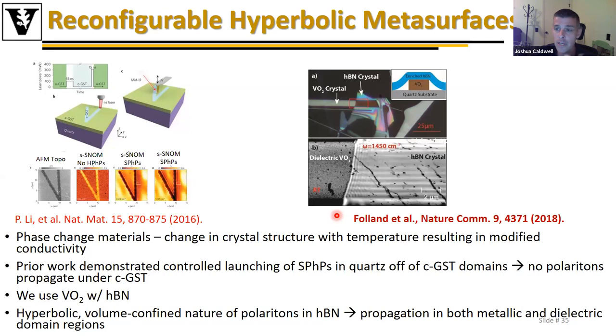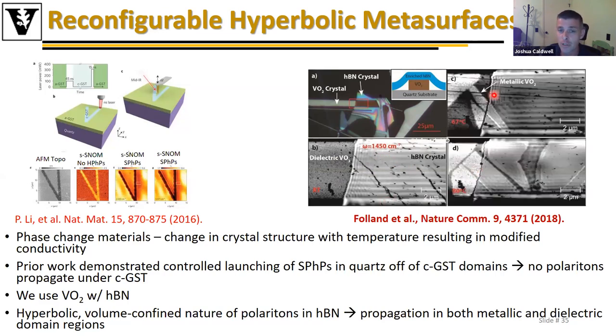So we then transitioned and said, if we used hexagonal boron nitride, a hyperbolic medium where the modes propagate through the volume, can I now use this for the same purpose, but using vanadium oxide as my phase change material? So here we have a single crystal of vanadium oxide. We transferred a slab of hexagonal boron nitride onto the surface. And here's a scanning near-field optical microscope image at room temperature, where you can see these hyperbolic polaritons propagating inside the volume of this boron nitride crystal. But as I increase the temperature, I start to introduce these metallic domains.